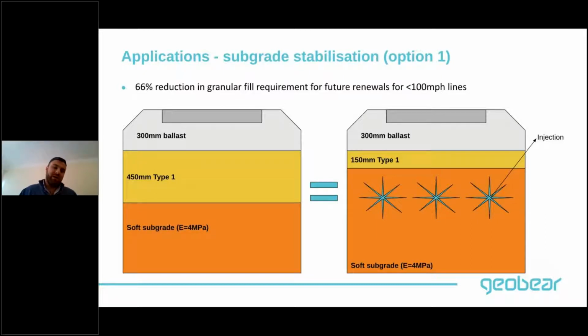You can, for example, utilize this methodology when you're coming to renew tracks. So if your track life has expired and you're coming to renew it, and you somehow have a soft spot or a soft subgrade underneath, you would require a thicker excavation. And with geopolymers, you can reduce that. For example, if you've got a subgrade modulus of 4 MPa, let's say, according to Network Rail standards, if you want to renew it and you've got a line that is less than 100 miles an hour, you would need 450 mil of type 1 plus 300 mil of ballast. That's the conventional standardized design.